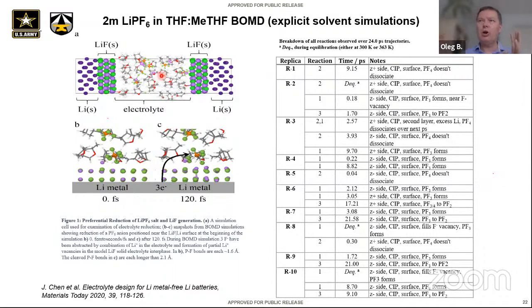They are well spaced in terms of time, decoherent, so the configurations are quite different, but we're also trying to sample realistic environments. Then Travis takes them, optimizes them to change from MD to the DFT bond lengths, and thermalizes at lower temperature, and then finally at 333 or 363, and then proceeds with simulations. One of the observations is that you can't start with pretty much whatever you want, there is a correlation between structure and reduction process, which we are going to see.